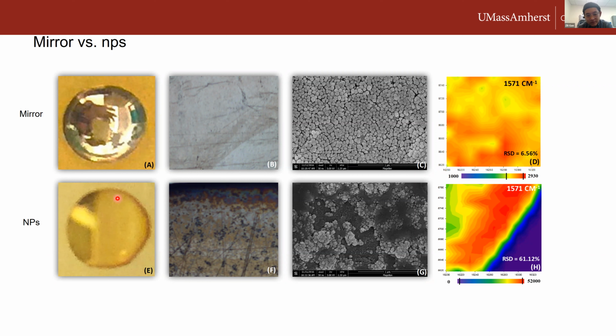If we look at the area without the mirror, we can see that we don't detect any useful signals. All of these peaks are coming from the background. The same with the red 40 ring, they're pretty identical. We didn't detect any useful signals. They're all coming from the background. But if we look at the area with the silver mirror, the mirror greatly enhanced both the red 40 signal as well as the saffron signals.